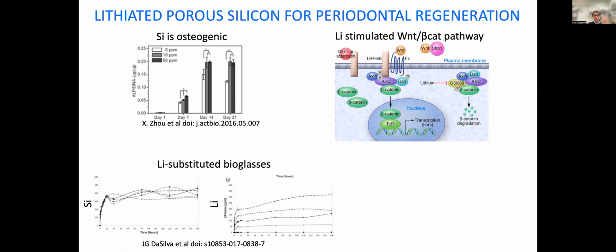In fact, this has been known for quite some time, and in the literature, a lot of people have been trying to use lithium substituted bioglasses to combine the release of silicon and lithium and stimulate regeneration in complex bone and ligament tissues. The disadvantage of using bioglass is that you can't really control the release of your ions from it, because the process is a process of leaching. So you have a lot of release of ions in the very early stages, and then nothing else gets released anymore. And in particular for lithium, you're also limited in the maximum amount of lithium that you can introduce in a bioglass, up to maximum 5%.